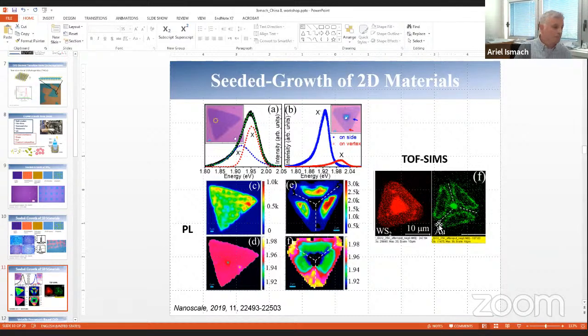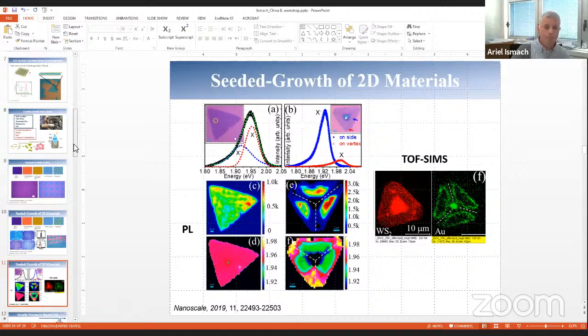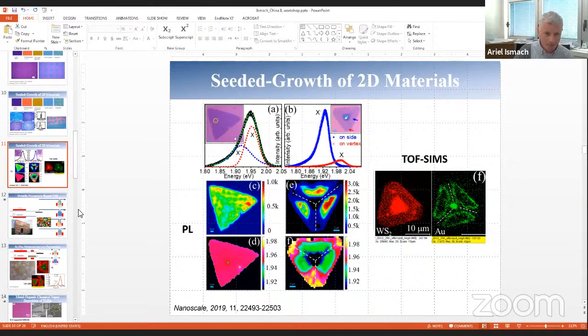We can correlate the position and the concentration of the gold along the domain with the PL, both intensity and shift. We are not going to talk about that in this talk, but the point here is that if you're not aware of that, the metal may diffuse into the domain and greatly affect the physical properties, in this case the optical emission of these domains.